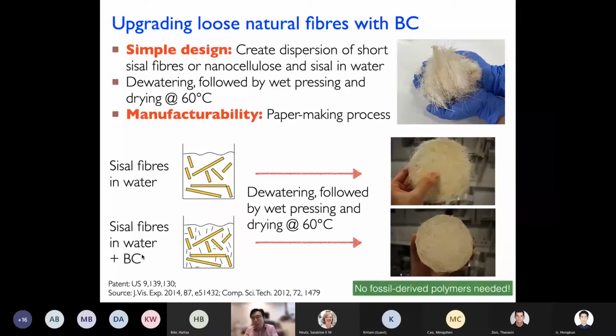The manufacturability aspect is the fact that it's a simple paper making process or wet laying process. So it's nothing fancy in terms of manufacturing. You filter and then you press dry them and you get a natural fiber with bacterial cellulose as the binder. So on the bottom here, you have about 10% bacterial cellulose binding the whole sisal fibers together. This middle picture here doesn't have bacterial cellulose, but rest assured that it is very, very soft and very, very weak. You can see that it is about to fall apart. The key thing here is that we don't actually need any polymeric binder, in the sense of fossil-derived polymeric binders, to bind loose fibers together in this aspect.